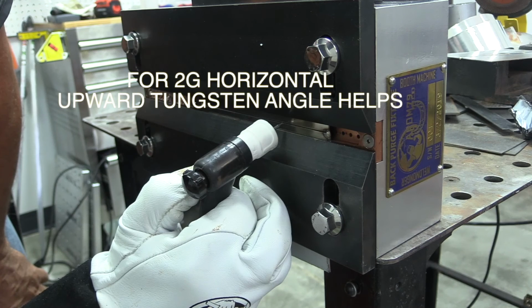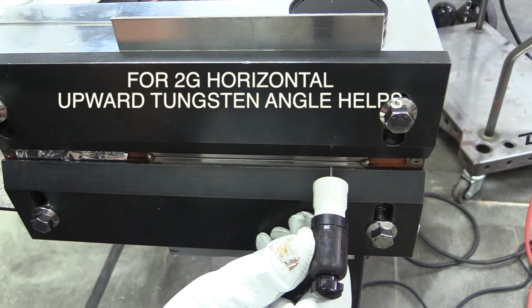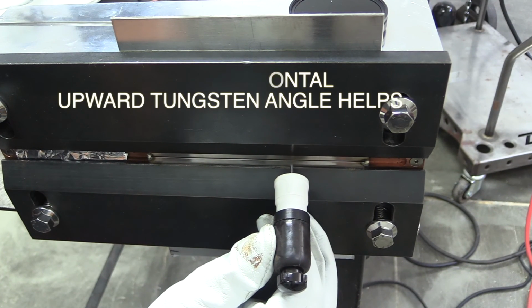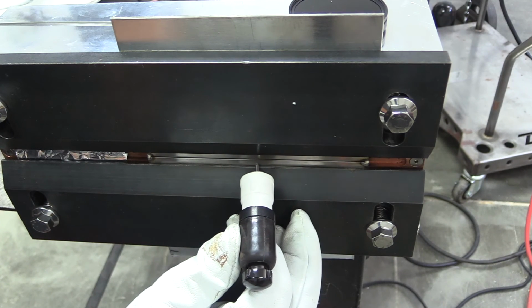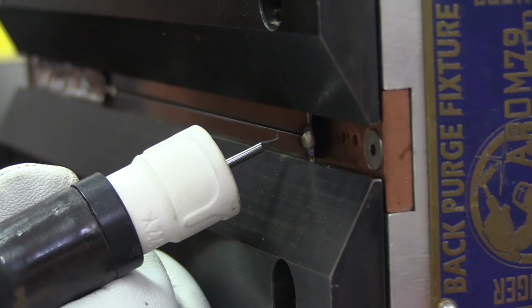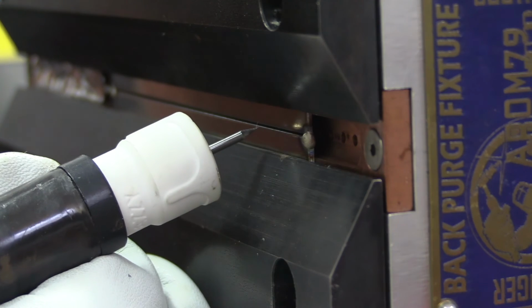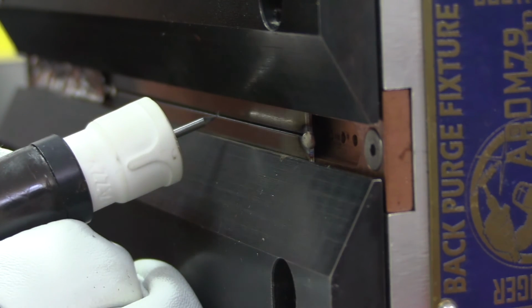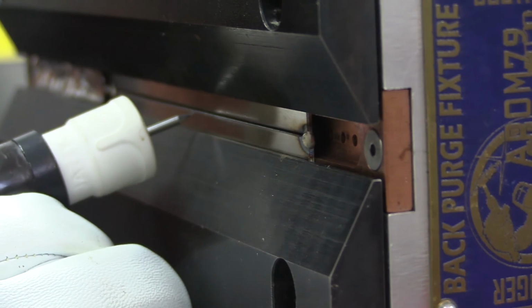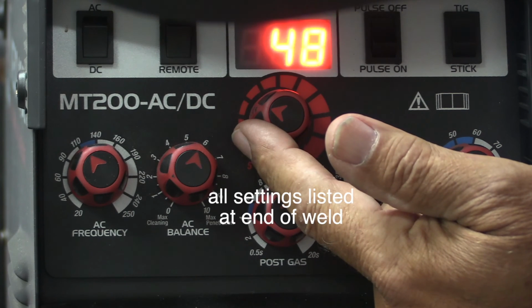Once I've got the tacks on it, I set the fixture up in the 2G position, and here's a really important tip. You want to angle the torch, angle the tungsten upward. For a horizontal weld, you don't want to have it straight in or pointing down, but pointing upward like this will help the argon reach the joint, and for some reason it just helps pass X-rays.